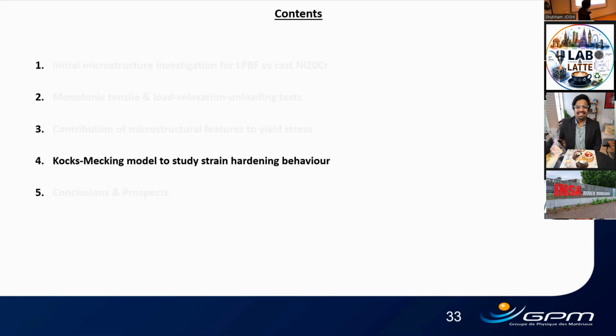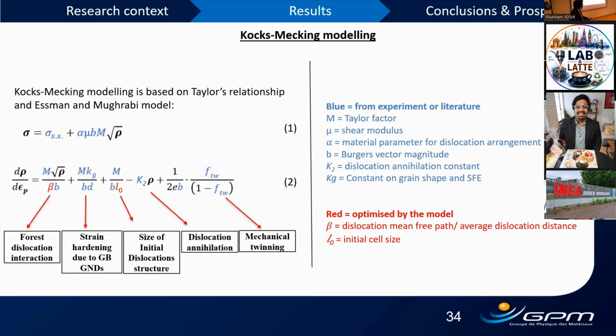But when it comes to the second question, what happens to strain hardening? Are these features, dendrites, still responsible for strain hardening? And also, could we model it? Spoiler alert, dendrites are still the most responsible factor, but let us look at how. To answer this question we used the Kocks-Mecking model, depending upon Taylor's equation and the Essmann-Mughrabi model. This Essmann-Mughrabi model is nothing but a modification of Orowan's equation, and it depends on the change in dislocation density with respect to plastic strain. In other words, this is the dislocation production mechanism: as we go in strain, how dislocations are produced.